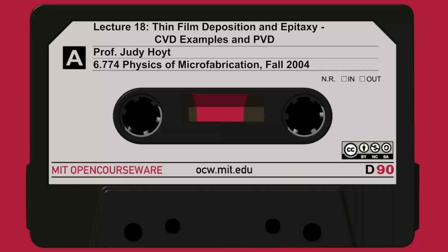Probably the most important reason why evaporation is not used in semiconductor manufacturing anymore is the step coverage is very poor. It's pretty much line of sight. So if you're trying to fill a trench, for example, in A here, and let's say you uniformly want to deposit the material all along the trench, because of shadowing effects, as this aluminum or whatever it is comes down, it's pretty much just going to deposit right here. It's not going to hit the sidewalls. So if you need this conformal deposition, you're not going to be able to get it by evaporation. You're going to need to use sputtering.